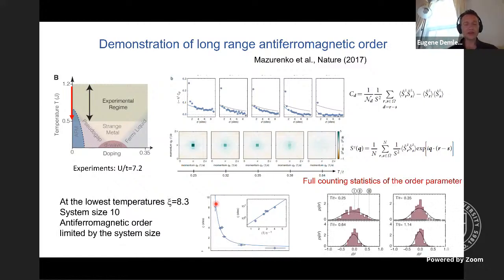What is special with cold atoms is that because we get an image, we can analyze not just the 2-point correlation function, but also higher-order correlation functions. In particular, we can look at the full distribution function of staggered magnetization. You can see that not only the 2-point correlation functions change, but also higher-order correlation functions change. To begin with, there is a lot of self-averaging, so staggered magnetization is very close to 0, whereas at the lowest temperature it becomes a much broader distribution. And in fact, you can already check that simple thermal fluctuations would not be able to account for this physics. You really have to take into account the quantum nature of spins.